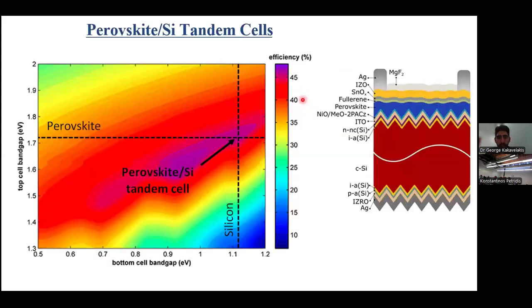According to theory, the maximum efficiency for this type of device, perovskite silicon, is approximately 45%. And indeed, so far we have managed to achieve close to 34%. So we are very well on track. We have already broken the Shockley-Queisser limit, of course, this is for the single junction, which is 33.3.